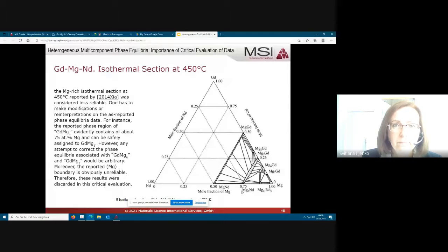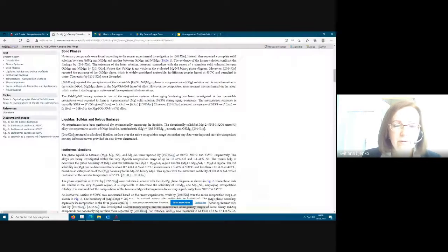And then we go back to this document, and we see that the existence of this solution cannot be accepted by our authors. The neodymium magnesium 5 phase is not stable in the magnesium-neodymium binary systems. And therefore, this was rejected and not accepted by our authors.